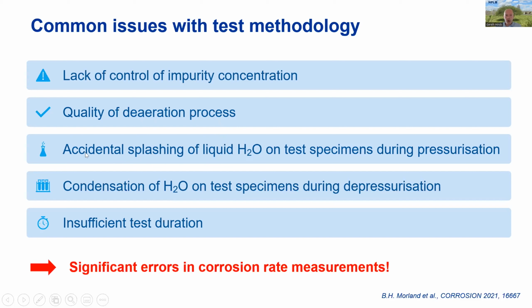A third problem is that when we pressurize the autoclave, if we have liquid water at the bottom of the autoclave before the test starts, the force of the dense phase CO2 entering into the autoclave can actually impact on the liquid water and splash it all over the test specimens. And this is something that is non-representative of fluid in the pipeline and leads to higher measured corrosion rates than reality.